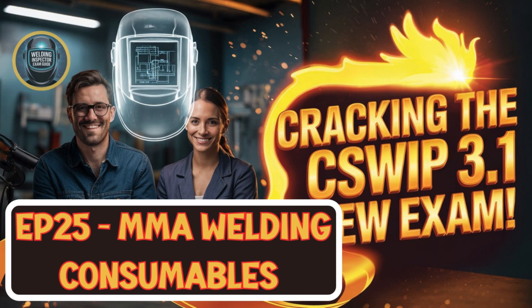And maybe most critically for certain applications, it controls the hydrogen content. Hydrogen. Why is that so important? Because too much hydrogen dissolved in the weld metal can lead to a really nasty defect called hydrogen-induced cold cracking. It can happen hours, even days after welding, and it seriously compromises the joint. Okay, that sounds bad. It is. So controlling hydrogen is key.